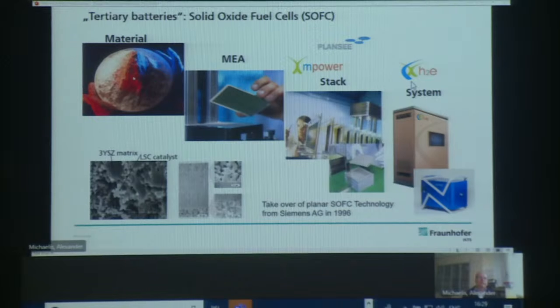And here you see the SOFC value chain. The core element is zirconia, the yttria-doped zirconia, which is oxygen conducting. So this is the electrolyte material. By tape casting, you make such a membrane electrode assembly out of this. You see a 10 by 10 centimeter sheet. And by screen printing, on one side, you deposit nickel oxide, on the other side, lanthanum strontium manganate. It's a tenth of a millimeter thin, and this component then gives you 30 watts of electrical power if you have oxygen on one side and hydrogen on the other side.